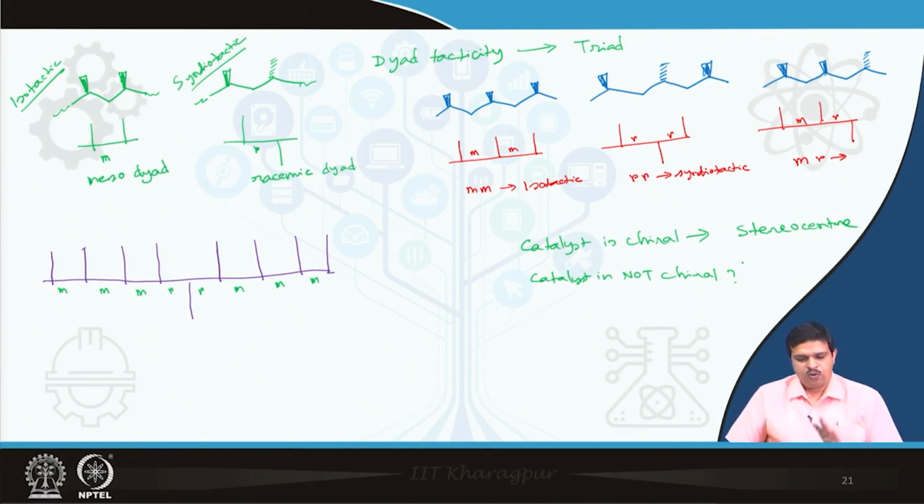Okay. So, in our polymerization by metallocene chiral or achiral catalyst, you have to have a good concept of tacticity, because only in this way can you study and conclude in which mechanism the polymerization is happening, whether it is catalytic site control or chain end control.